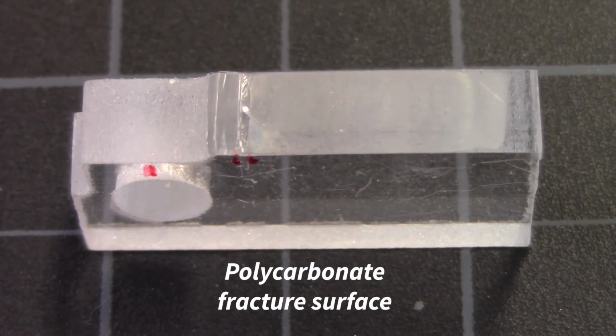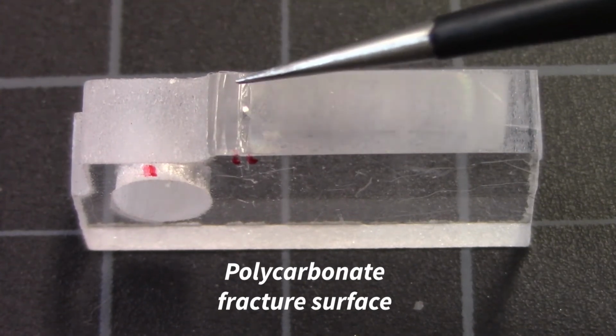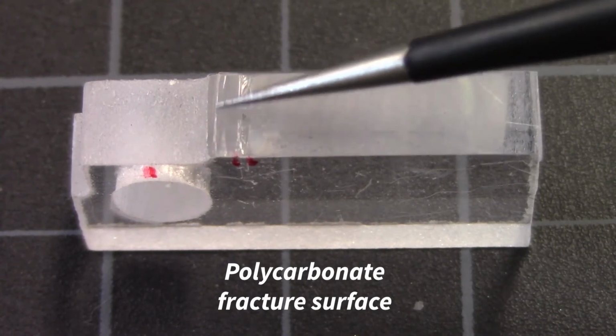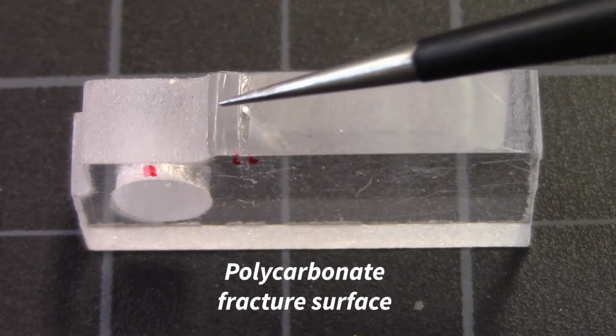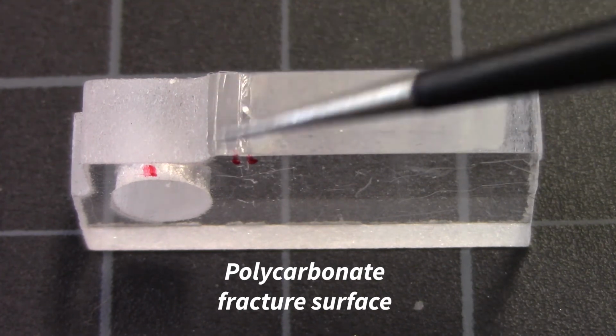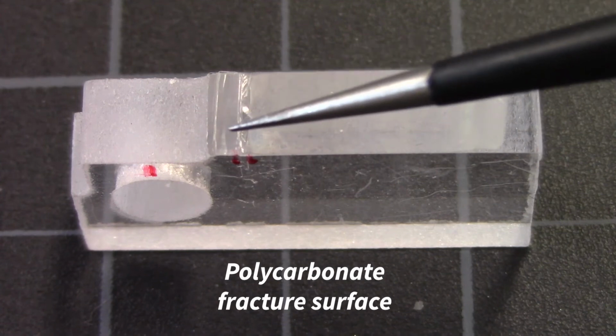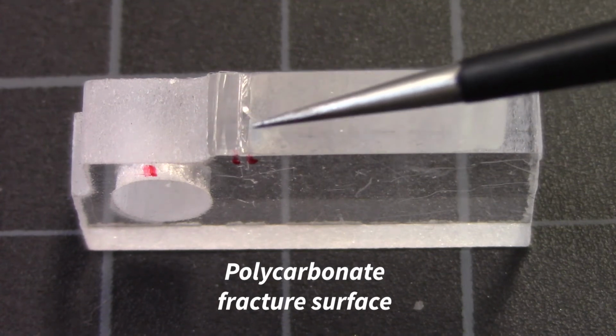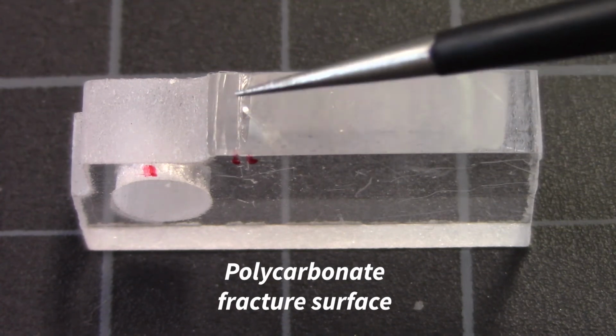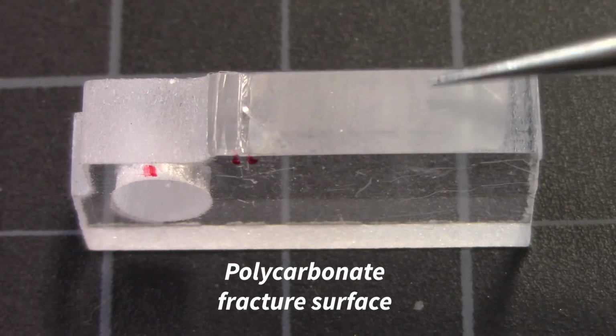And here's the polycarbonate specimen. You can see the same features here. Our starter notch edge, our pre-crack region, smooth shiny surface, and then a crack propagation region with a few more striations, and then our fracture surface here.